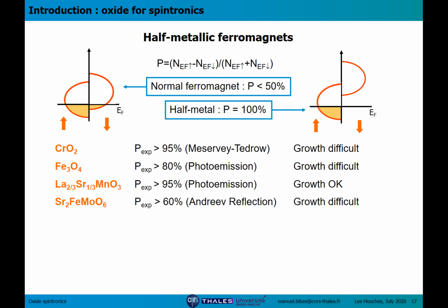Fe3O4 was, I think, the first material that was predicted to be half metallic, in the early 80s, I think in 1984. It is expected to be half metallic, but again, it's quite difficult to grow in the single crystalline form because of the presence of antiphase boundaries. There were results showing spin polarization values of about 80% using photoemission. But for magnetic tunnel junctions, I think the best results were never much more than 50%.